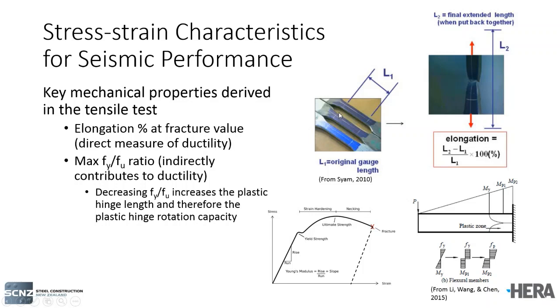The sample is then put into a tensile test machine, and we get this sort of behaviour for structural steels. Once we start loading them, you'll typically get elastic, recoverable deformation. We'll reach a yield point, and then we'll transition into plastic behaviour where the steel will continue to deform without any additional stress. Then the steel starts to strain harden, and eventually it will reach what's known as the ultimate strength, which is the highest stress. Once we reach this ultimate strength, the sample will start to neck down, and it will eventually fracture. After the test is complete, the test sample is essentially put back together again.